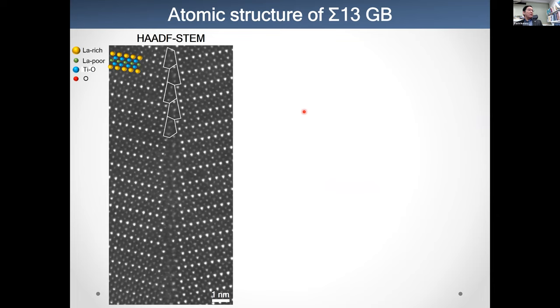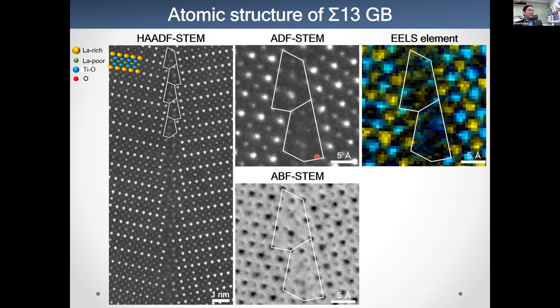On the other hand, what happens for sigma 13 grain boundaries? Again, you can see lanthanum-rich layers and lanthanum-poor layers, rich, poor, rich, poor layers, alternately stacked like that, and forming this kind of structure, the sigma 13 grain boundaries. This magnified image of the sigma 13 grain boundary is a little bit different because the structure is not clearly imaged. That means distortion occurs inside the structure unit.